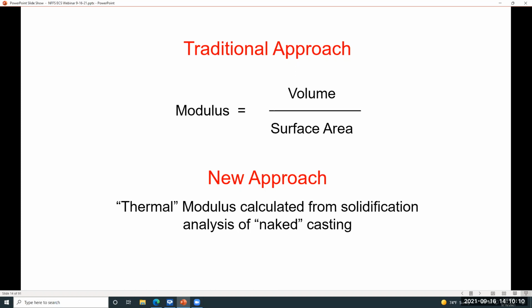However, in the computer age, we can do a lot better than that. We can calculate what we call a thermal modulus or an effective modulus, which is based on an actual solidification analysis based on the actual properties of the casting alloy and the mold materials in question. This gives us a more accurate analysis and thereby allows us to go back and do a more accurate riser design.